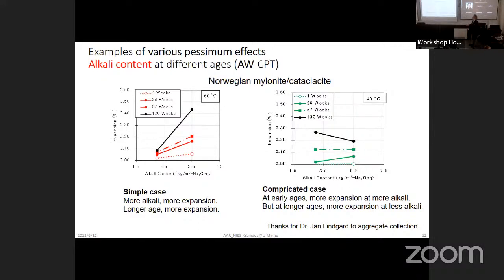And many people want to know the alkali threshold value, below which we can expect no expansion will take place. This is the reasonable case. According to this one, below 3.0, no expansion will be expected even over a long period of time. But unfortunately, this is a case of Norwegian mylonite, some deformed rocks. But this is a case of 60 degree, and this is a case of 40 degree.